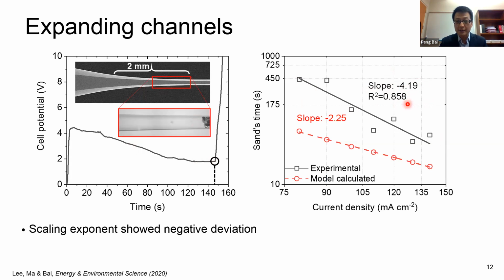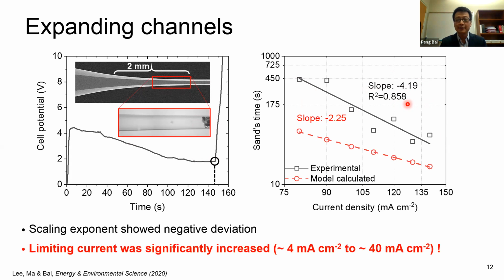So what's the significance of this? The significance is that when you have this negative deviation, you actually increase your system-specific limiting current by orders of magnitude. So here, for our regular capillary cell, going beyond 1 milliamp per centimeter square can trigger diffusion limitation. But if you have the expanding channel, you have to go even beyond 75 milliamp per centimeter square to really see a clear transition of growth, to see the depletion of concentration, to see the diffusion limitation. So that tells us maybe we can engineer some structure so that along the penetration path, you will degrade back to some safe current density.